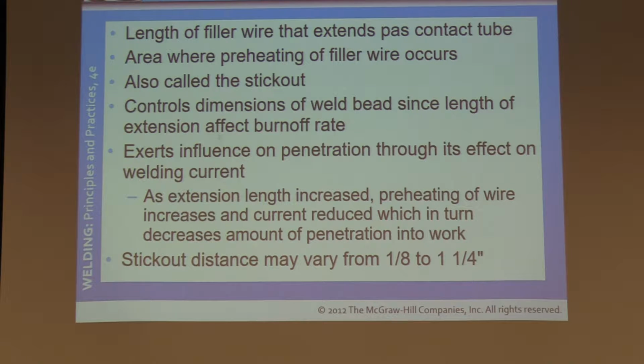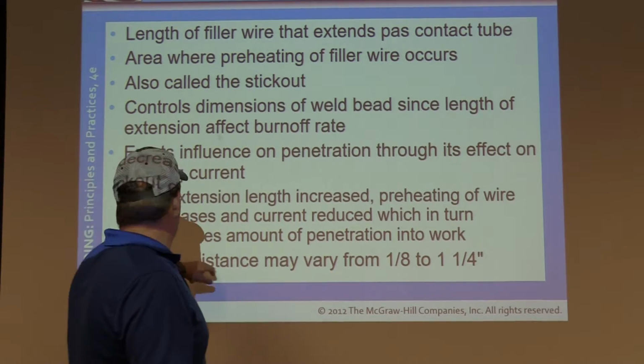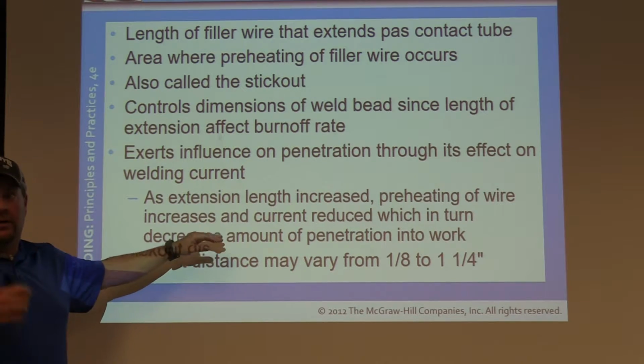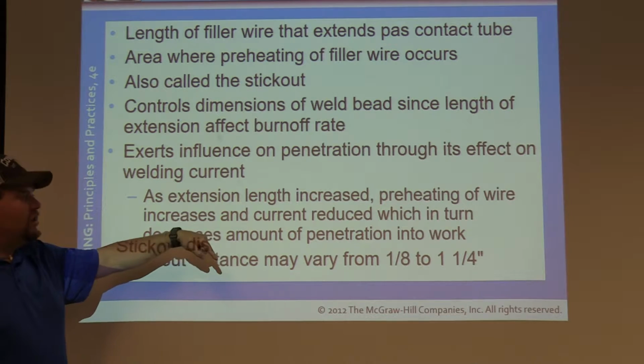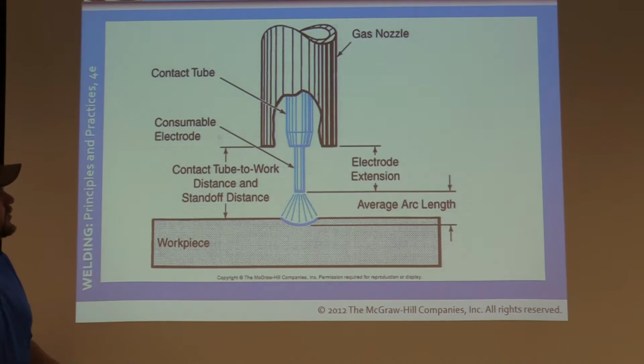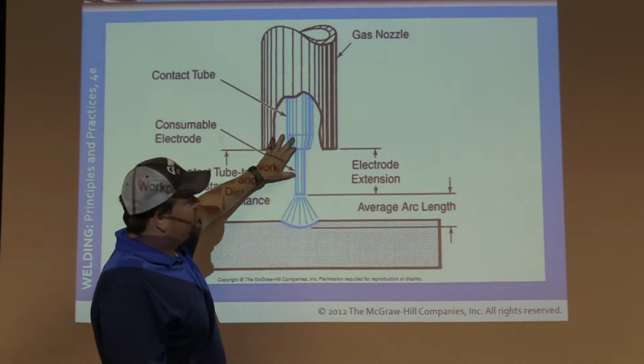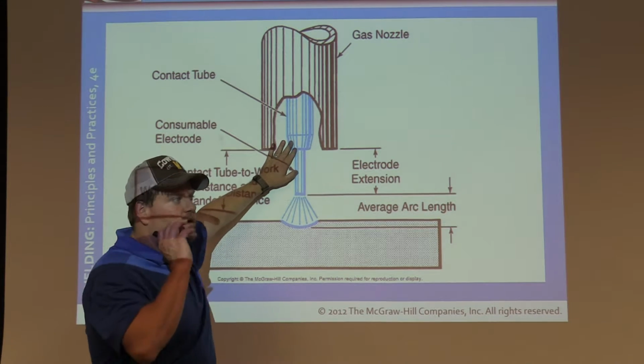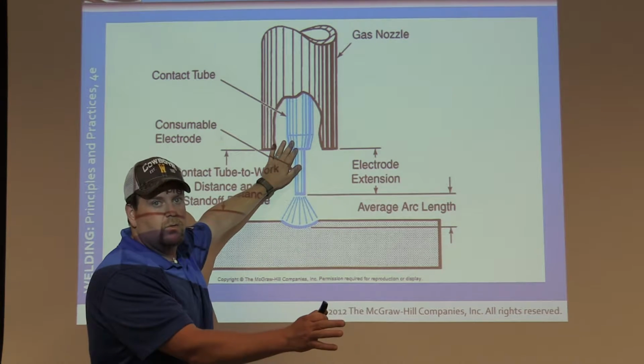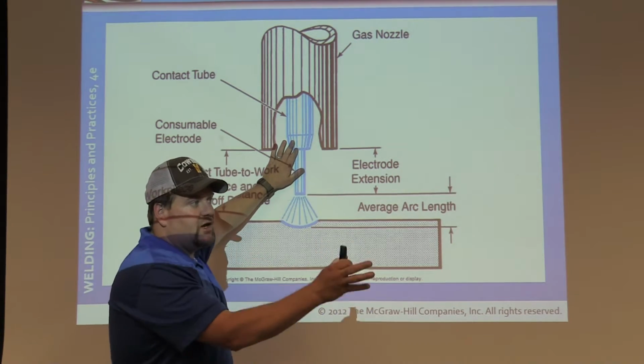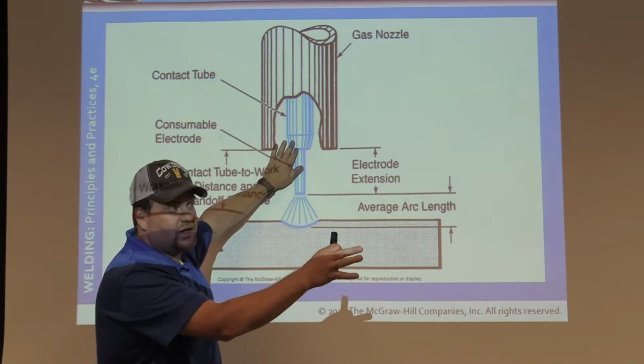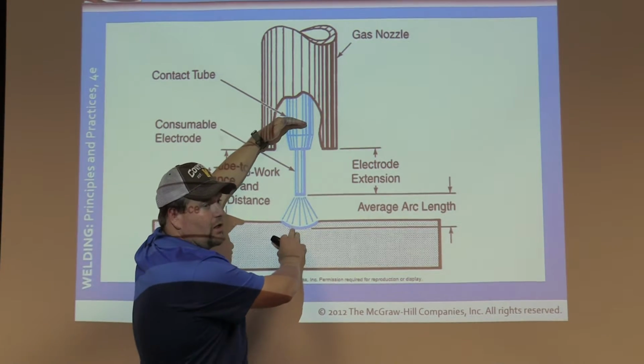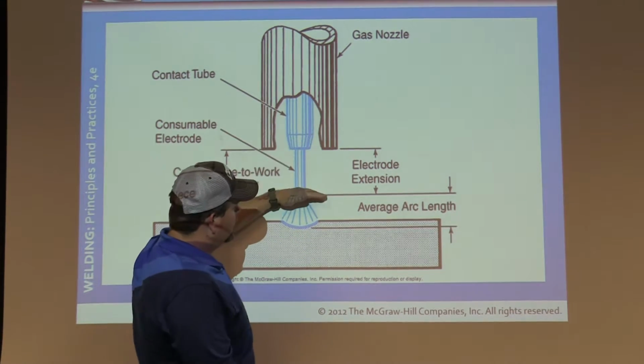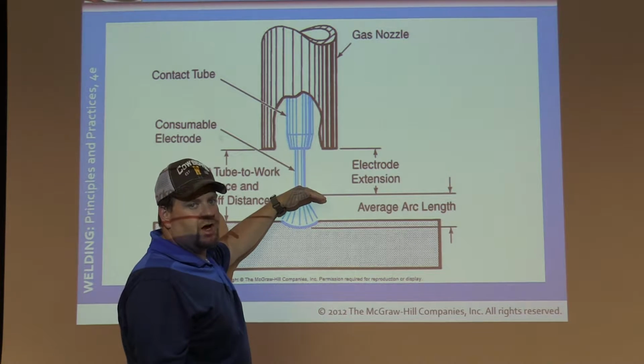As the extension length is increased, preheating of the wire increases and current is reduced, which in turn decreases the amount of penetration into the work. So, real quick, the further we get away, less penetration, we start having problems. The closer we get, the more voltage is there. Real quick, very simple. This is a path of resistance, okay? Anytime we're sending electricity further away, we're losing electricity, whether it be amps, voltage, whatever. The further we send it, the more we lose or the harder it is to get it there. So if you have it a long ways away, you're going to get less penetration, less heat. You get it in closer, it's going to be hotter. It's also going to have better penetrating values.